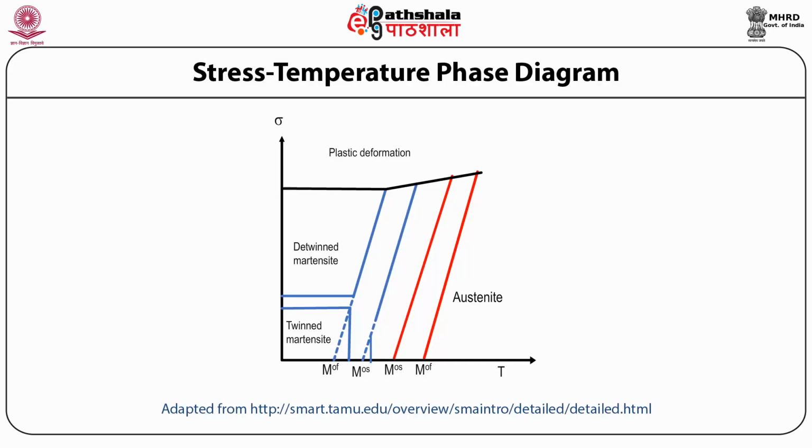It also hints at the formation of stress-induced Martensite, where Martensite can be produced only by applying stress and without changing temperature.